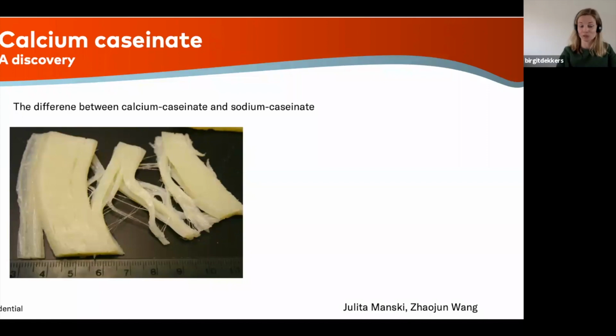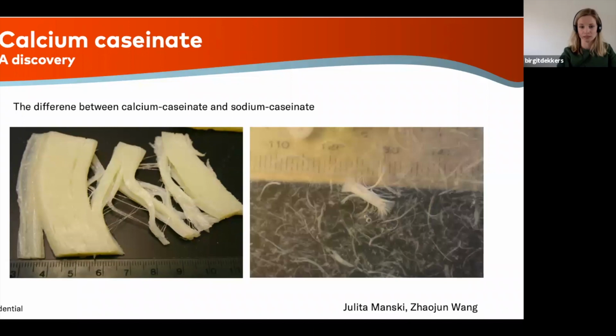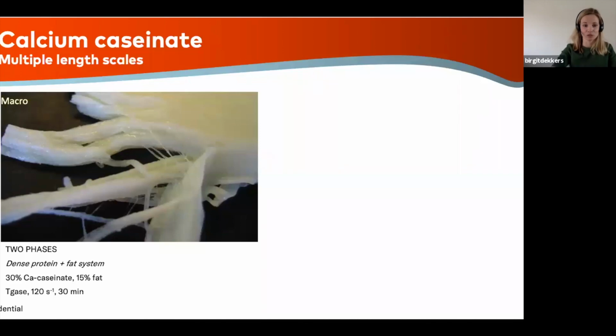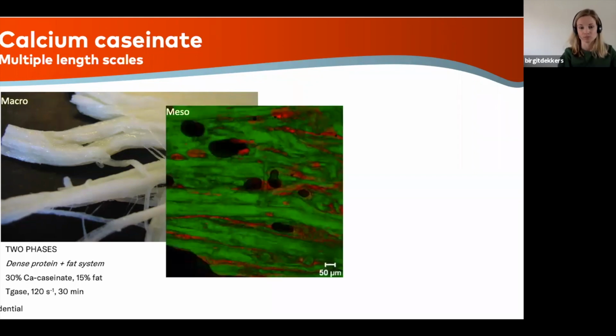So these are calcium caseinate structures where you see a very nice fibrous structure on a larger length scale, as you can see on the ruler on the bottom. Thick and thinner fibers that you can even pull apart very nicely. This study was further investigated with also adding a second phase, which is fat. So you had combinations of proteins and fat, and at different shear rates, different times, different concentrations. And this all led to very nice and interesting structures on different length scales.